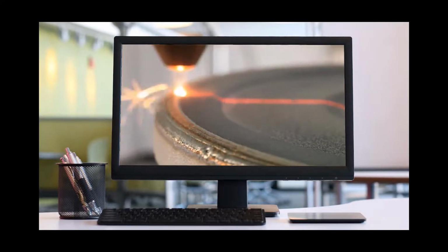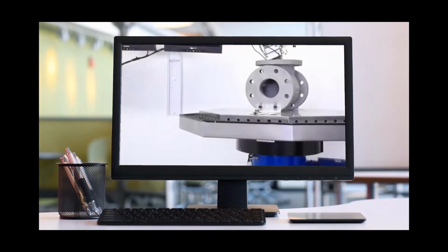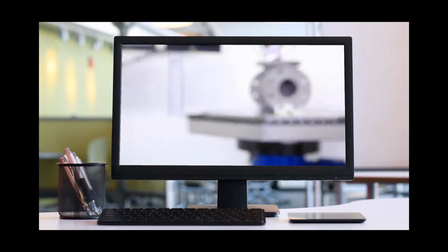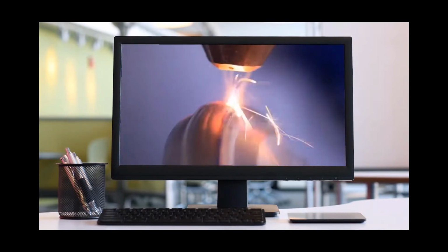Probably the most significant advantage of laser-applied powder over HVOF or thermal spray processes is that we have a true metallurgical bond, meaning we create a weld pool and do not rely on a mechanical bond, such as in thermal spray applications. Therefore, the likelihood of chipping or peeling is significantly reduced. Joining Technologies is most often called upon when the challenge is significant and the risk is high.